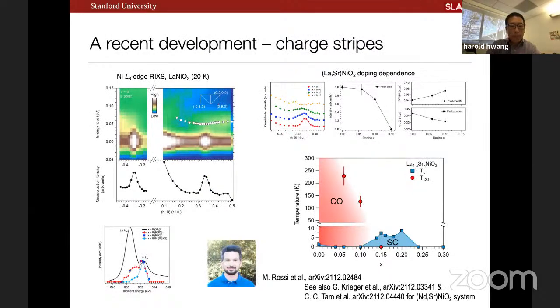A recent development in this field has actually been the observation of charge stripes. And so for the focus of this series, this again is a very familiar concept to you. So let me just flash work of Matteo in a slide here. Again, looking at RIXS, the basic feature is that we see something at about a third wave vector, a charge peak.